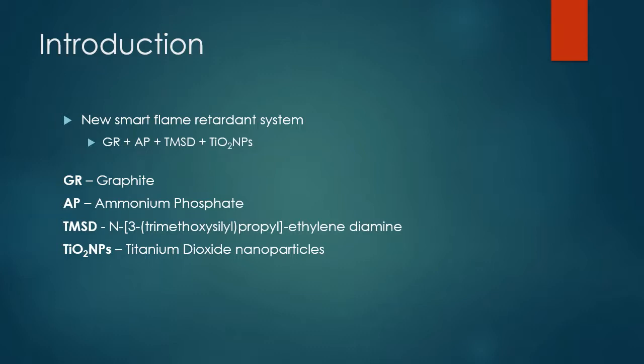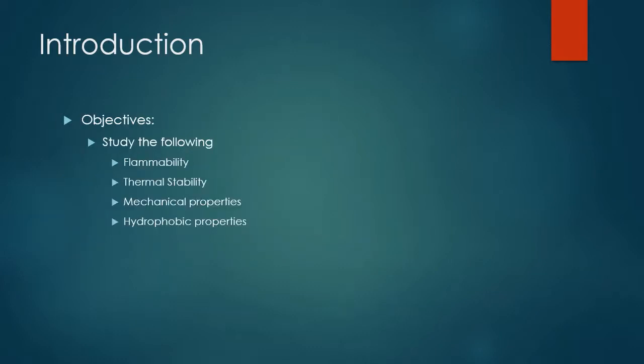And for this paper, we have the new smart flame retardant system we will use, which is a mixture of graphite, ammonium phosphate, 3-trimethoxysilyl-propyl ethylene diamine, and titanium dioxide nanoparticles. Our objectives with the new flame retardant system would be to study its flammability, thermal stability, mechanical properties, and hydrophobic properties. We will see which one improves or if it retains, and we will see overall if the incorporation of the flame retardant materials is actually successful in the textile fabric.